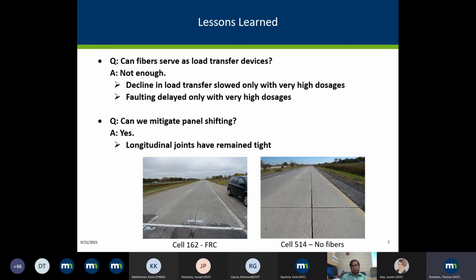Can we mitigate panel shifting? I would say yes, we have seen evidence of that very much. Even, I believe, Illinois has reports showing that when they put fibers in, you do mitigate the panel shifting that goes on. And we even have it at Minroad here, you can see on the right-hand side, the section where it had no fibers. Over time, those panels, once they lose the bond, they start shifting towards the shoulder. But on the left-hand side, you can see the fibers are holding them together very well.